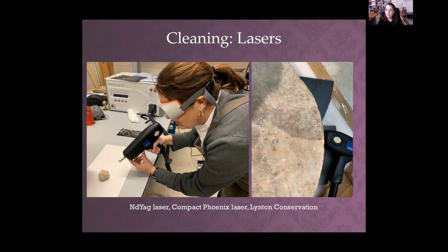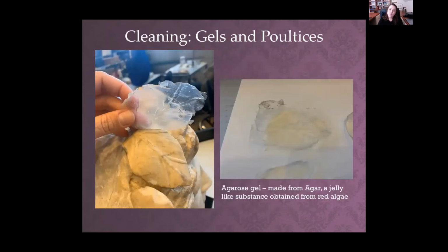Something interesting about the laser cleaning that we weren't expecting was that the leaves and the berries had this orange tone to them when we were done, which was not acceptable. And anecdotally, talking to a number of people who have used the lasers on stone in the past, we think that was probably some of the wax layers, some of the organic treatments that were put onto the sculpture that turned orange after using the laser. And wonderfully, this agarose gel, which is made from agar, which comes from the red algae, was able to remove it. So much like Jen was telling you about the poultices of clay that were used previously, this is one that's made out of this agar gel. So it's very, very clean, and it does not soak into the marble. It pulls everything else without leaving a trace behind, which is wonderful.